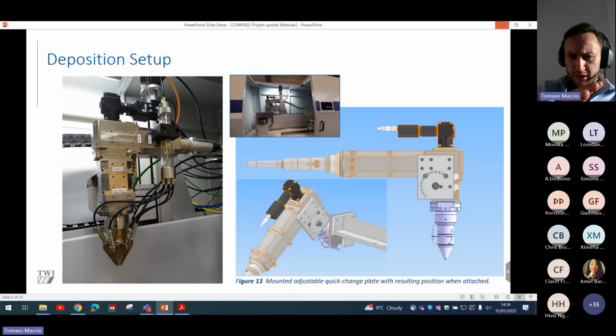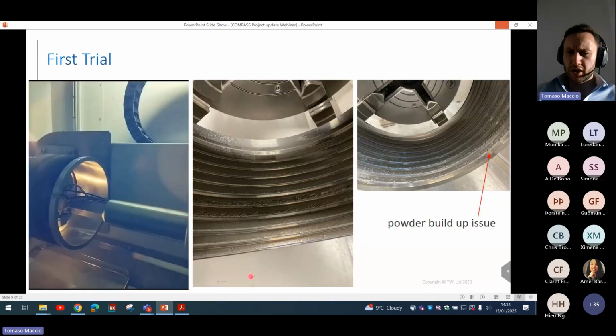So we set up a nozzle for doing the external deposition at first, to ensure that we were able to deposit the material onto the substrate material. We didn't get any cracking and we didn't get any porosity. So we wanted to do it in a step-by-step method to ensure we were getting the desired results. So the setup was complete here on the small scale machine. And then we did first initial trials on internal bore cladding on the small machine.